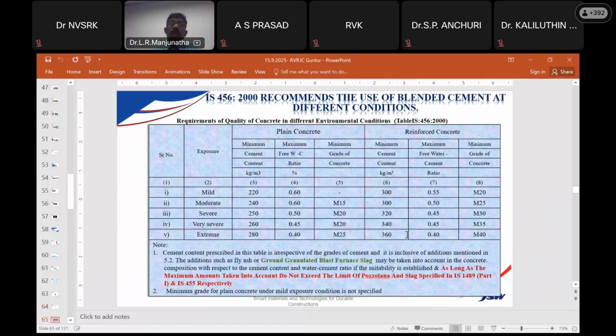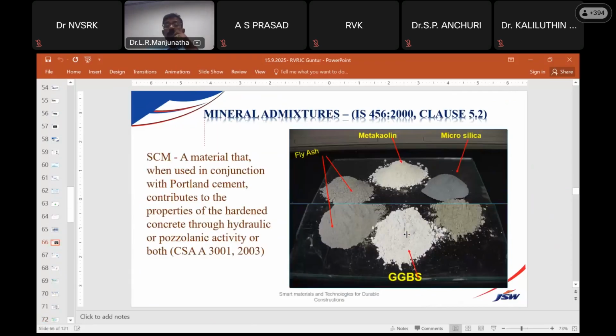So Indian code IS 456 also permits the usage of high performance mineral admixture like fly ash or GGBS in the concrete making. Fly ash you can start from 15 to 30% we can use. GGBS we can go up to 70%, because GGBS has both cementitious properties as well as pozzolanic properties. So these are the mineral admixtures. Already I had shown you the chemical admixtures. Mineral admixtures are microsilica, fly ash, metakaolin, and GGBS. These are very good